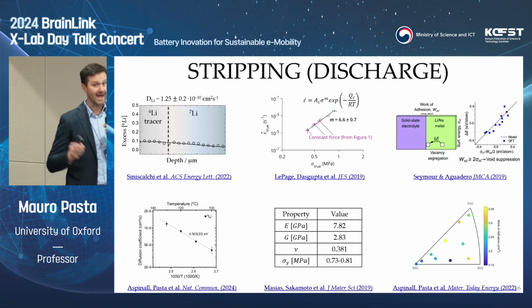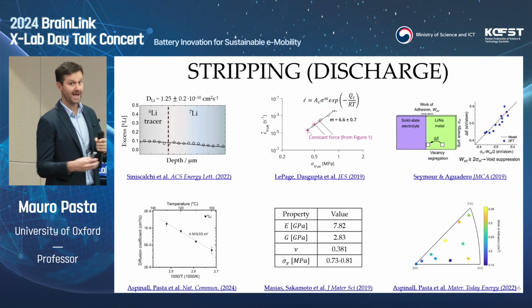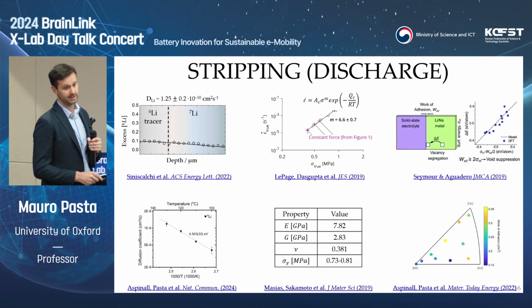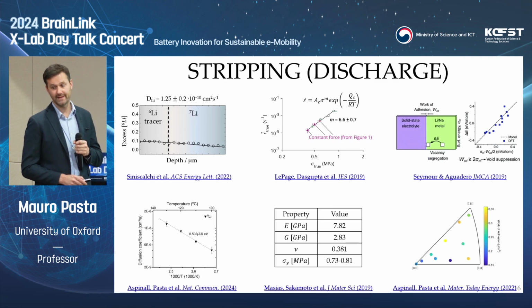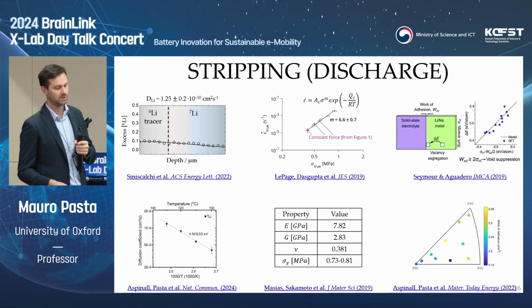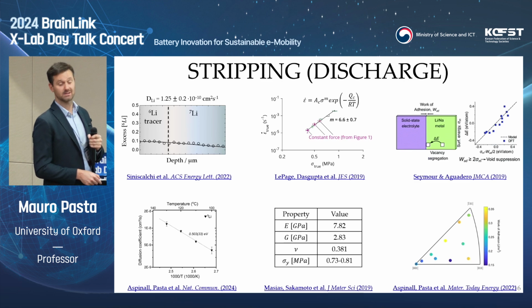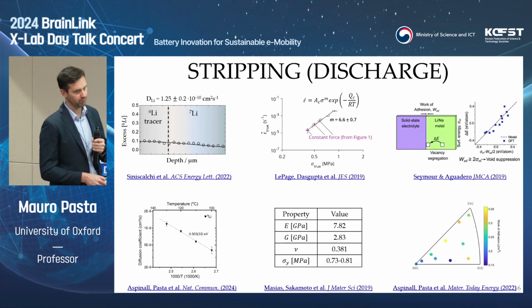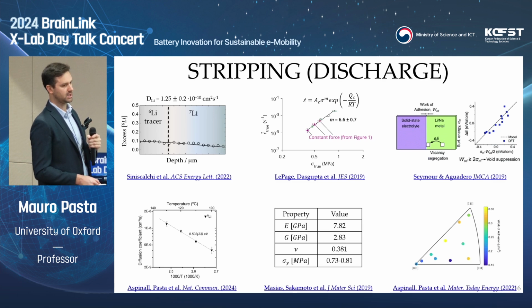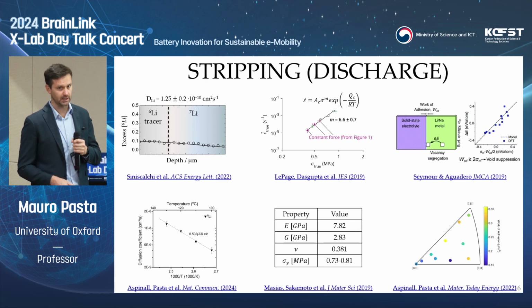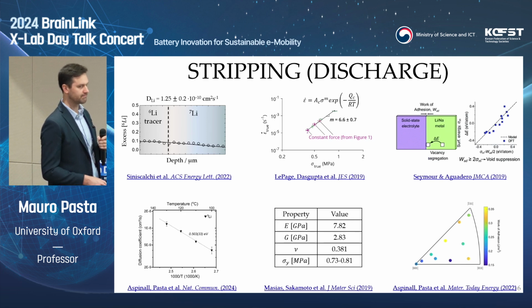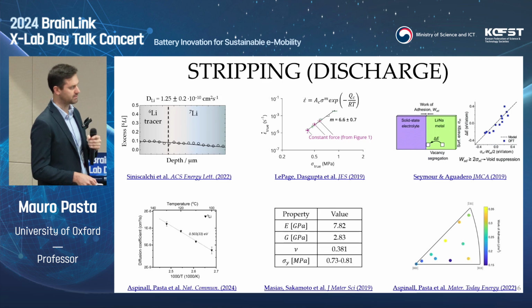Now, a key takeaway message: you can prevent voids from forming, so you can increase transport, if you increase temperature or if you apply high pressure, and that's what most of academia actually does right now. You operate at pressures or temperatures that are not particularly compatible with a real-world application. For example, you see pressures in the order of megapascals very often in solid-state batteries, and that's a no-go for an implementation into an actual pack. So we are working under the assumption that we need to decrease the pressure below 1 megapascal. And if you look through the literature, very few groups are actually working at this pressure, as the problems are quite severe.